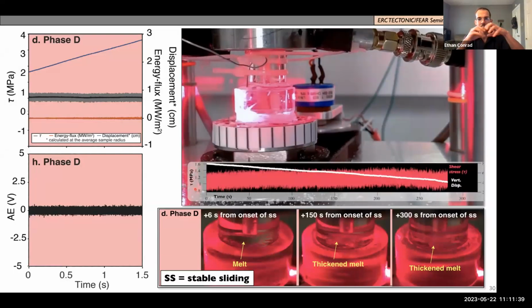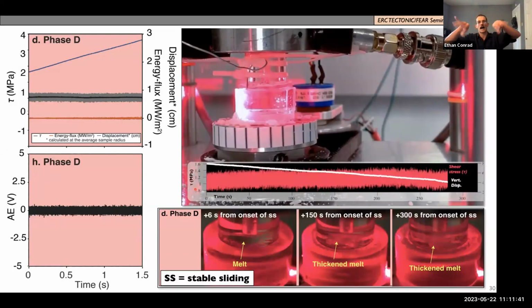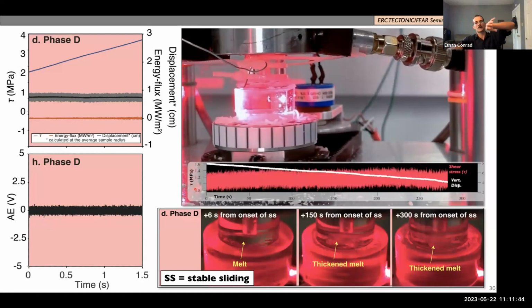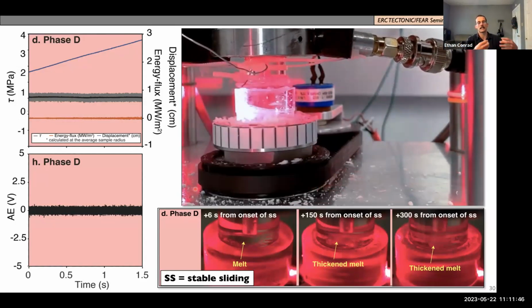You can see the ejection of powders at first, and those powders are forming material that melt can incorporate and include into the melt. So it's cool to think about how the powders are melting, are easier to melt, and form fuel for the melt in a way.